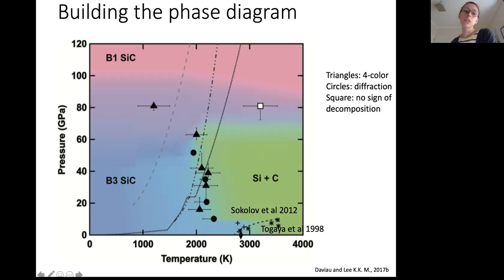Right, and so these two images up here, this was an interesting experiment because it was at pressures above this B1 transition. And at low temperatures, where the kinetics may be too slow to transition to the rock salt structure, we still see signs of decomposition. But at high temperatures, where the kinetics would likely have allowed the transition to the B1 structure, we no longer see those signs of decomposition, the diamond diffraction or those optical changes, meaning that potentially the B1 structure does not break up in the same way that the B3 structure does, with carbon coming out of the silicon carbide.